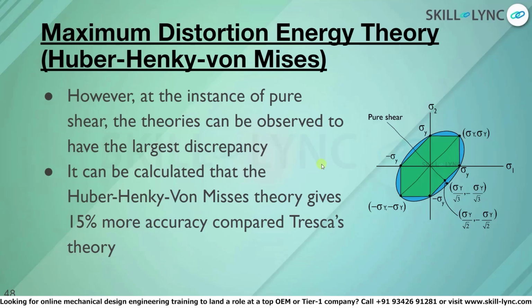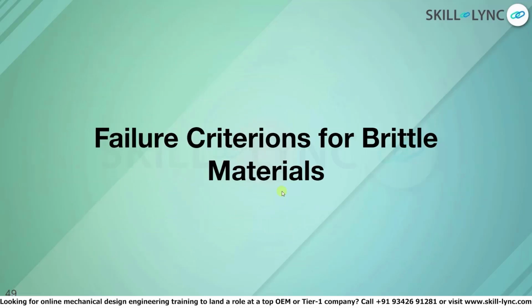But when it comes to pure shear, the theories can be observed to have a large discrepancy. Experimental calculations say that the Huber-Hencky-von Mises theory gives 15% more accuracy compared to Tresca's theory.